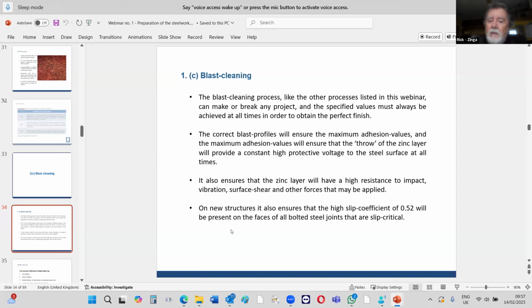And also the throw. So we mentioned here in the second point about the throw of the zinc layer. So Zinga has a throw of 15 millimeters. I don't have a blank panel here. Okay, but if you had a steel panel and you blast the whole panel and then you coat one half with Zinga, and this half you leave uncoated. If you then put it outside in the rain or by the sea for a couple of weeks, the blasted part will start to corrode and turn orange as normal and go rusty, but it'll corrode up to 15 millimeters from where the zinc stops.